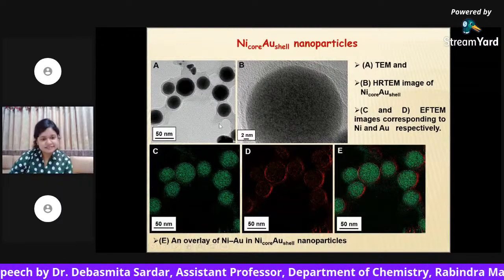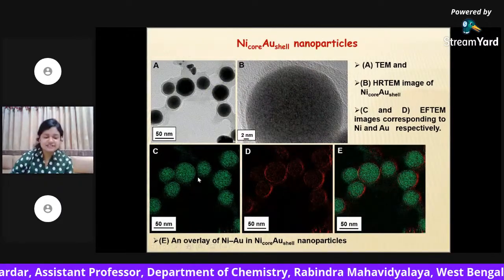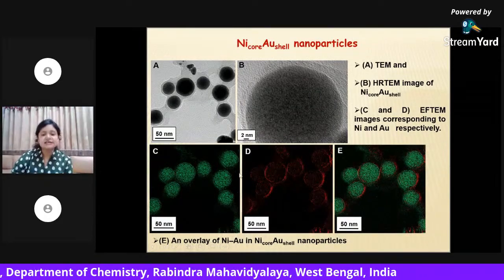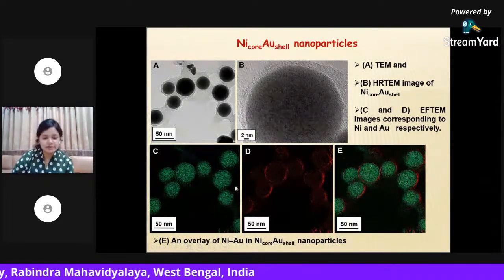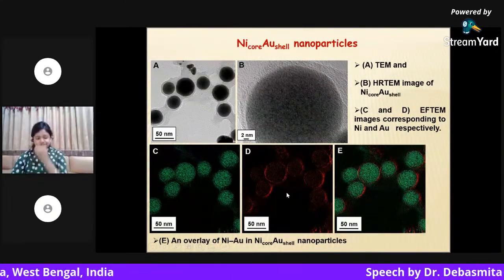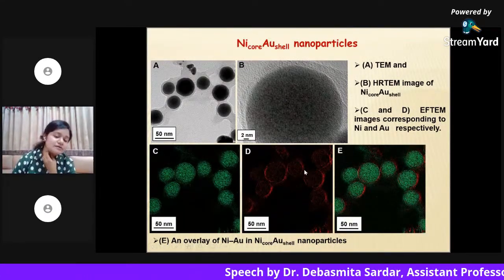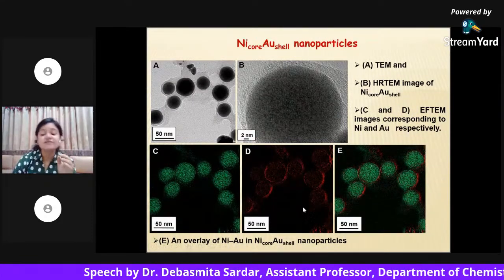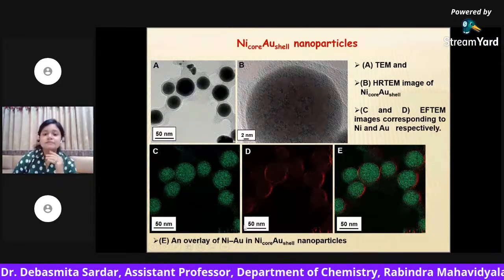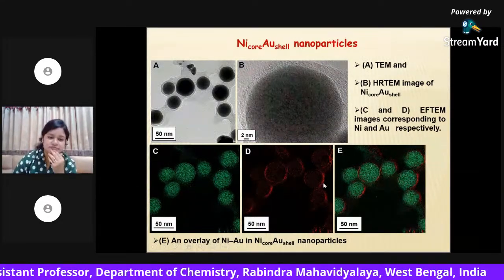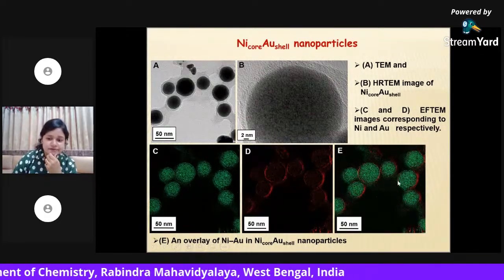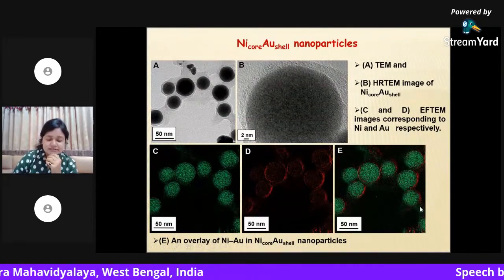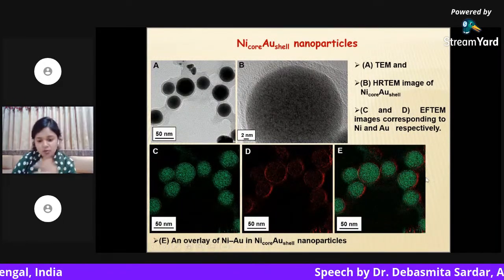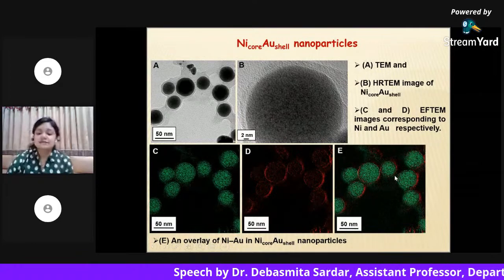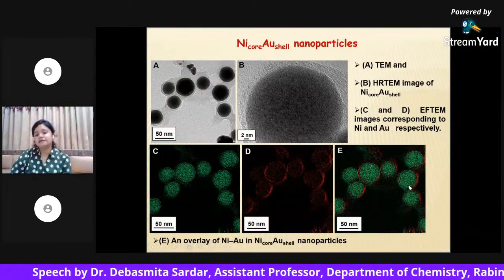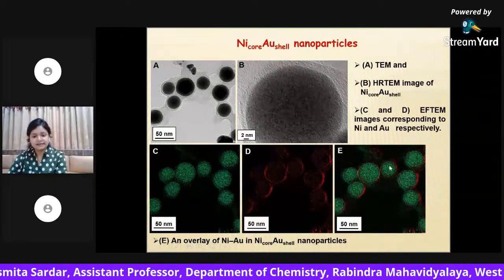Here I have synthesized, this green one is nickel. In picture C, the green one is nickel nanoparticles, and D is only gold nanoparticles. I told you that it is red, but it is basically a color just reflected from the machine. Really, gold nanoparticle is crimson red. The E picture is an overlay of nickel and gold, nickel gold nanoparticles. And you can see in the E picture that there is a red lining over the green nickel nanoparticles.